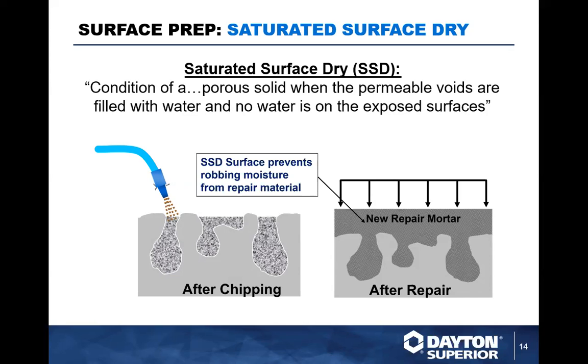When you mix up a repair mortar, it has water in it. So what concrete wants to do is suck the water out of the repair mortar mix and deprive the repair mortar of water, which is bad for the strength of the repair mortar. It robs the cement of its hydration. It doesn't cure properly. It chips out, it breaks, it cracks, common issues. So the saturated surface dry process, basically, think about thirsty concrete. You give the concrete a drink before you fix the concrete. Otherwise, it's going to suck all the water out of the mix and you're going to have a bad repair job.